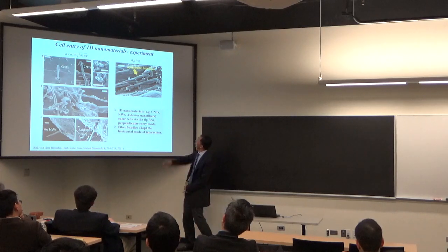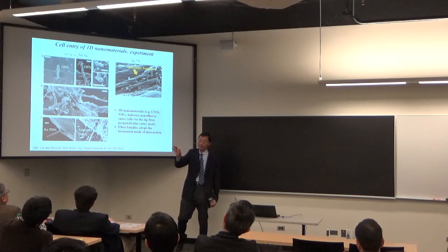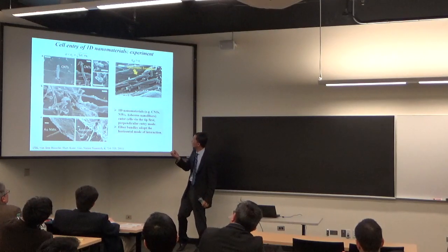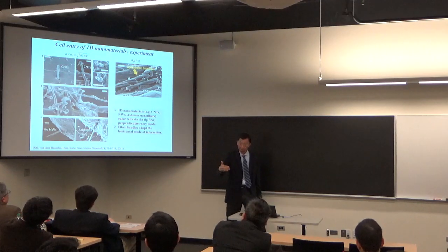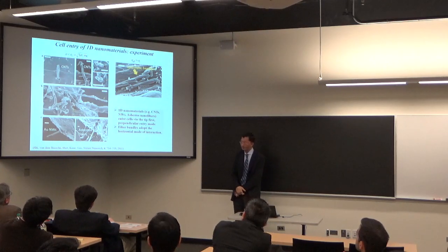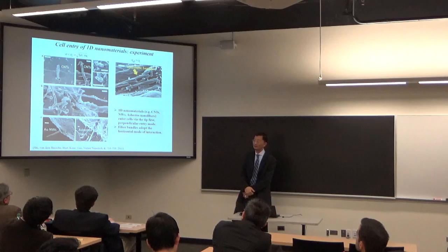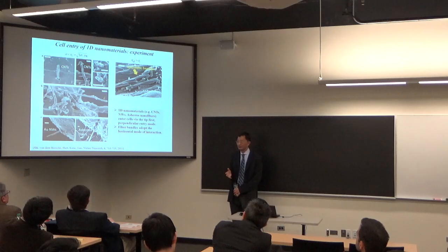Okay. And when we have bundles of these fibers, when you bundle these fibers together, we have an effective large radius. Then we find in experiments that those bundles tend to lie parallel to the cell surface. So this agrees with our theory. But an ideal experiment would be if you can feed the cell with a fiber, but the fiber is growing. It's like a cell interacting with a growing fiber. That would be an ideal experiment.